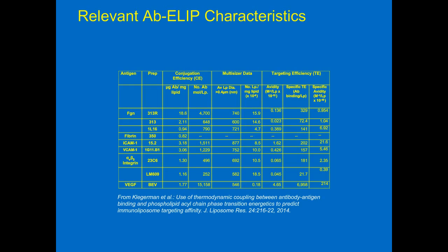So yes, there are quite a few different sizing technologies, and Coulter has a whole range of counters and sizers, and there are those designed for working with larger particles, such as cells. We use the Multisizer because, first of all, it will go down to the smallest size possible with the Coulter principle, which is about 400 nanometers.